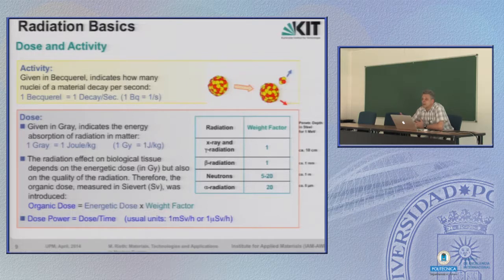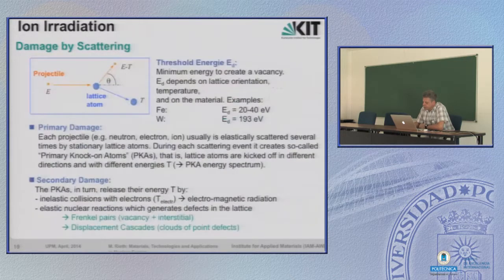So alpha irradiation is in principle harmless if it comes from the outside. It doesn't even penetrate a sheet of paper. But if we incorporate materials which emit alpha radiation, then you have a problem, because internally 5 microns are a lot, depending on where irradiation takes place. The dose power, that's the dose divided by unit time, and it's given in sievert or micro- or millisievert.